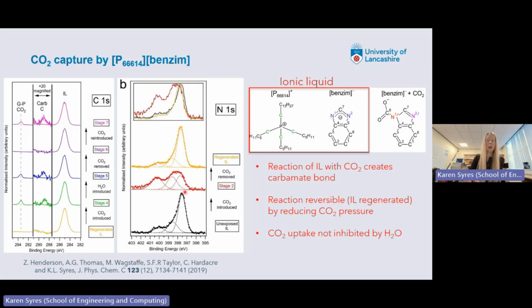We then introduce CO2 into our chamber, and we can see the shape changes dramatically. So this higher energy peak here comes up, and that is showing this bond here. So it's showing this carbamate bond that's forming when it reacts with the CO2. And then simply by pumping the CO2 back out of the chamber, it does then go back to its initial shape.